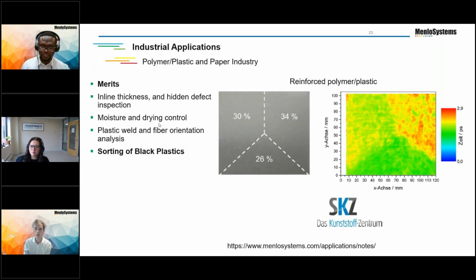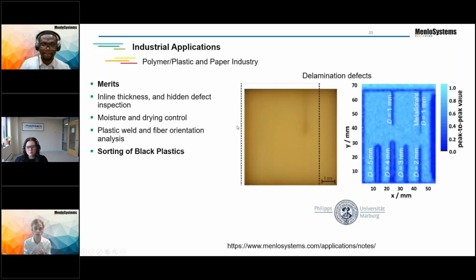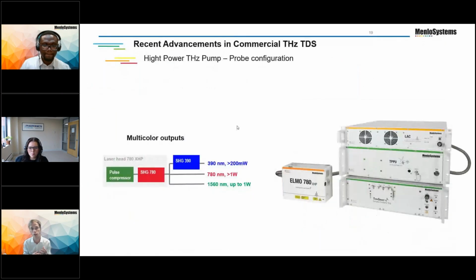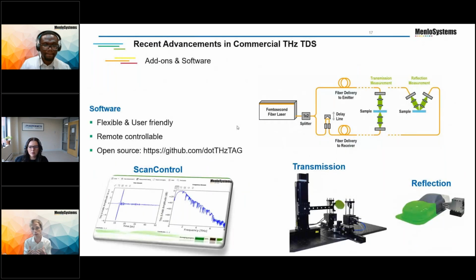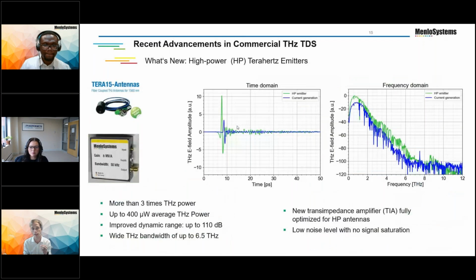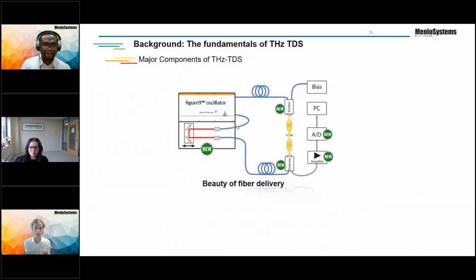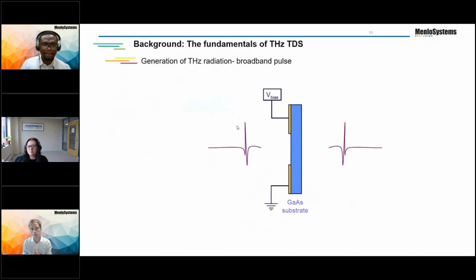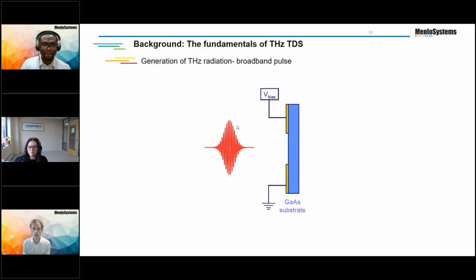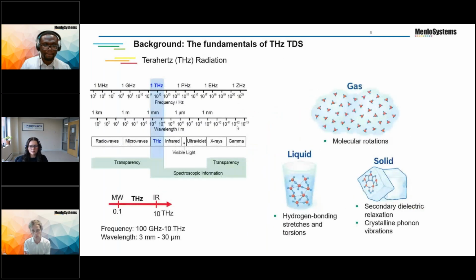So actually, this tends to be a spectral range that we at Menlo Systems really don't cover typically. We typically work very well at the infrared wavelengths, starting at 1 micron or 1550, and then we'll get out to the mid-infrared, where we'll go from, say, 3 microns out to about 15, 18 microns. And then from there, we generally will generate terahertz by using, as Prince was presenting, photoconductive antennas, which generally covers this 100 gigahertz to 10 terahertz range.